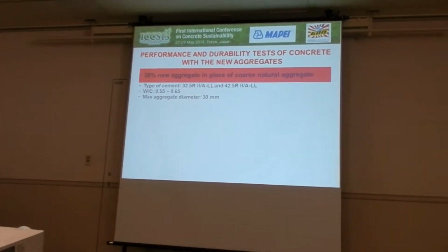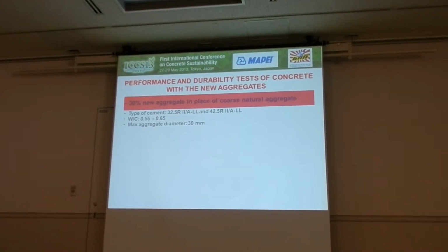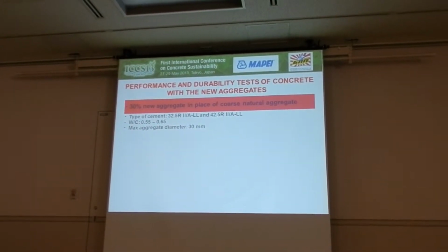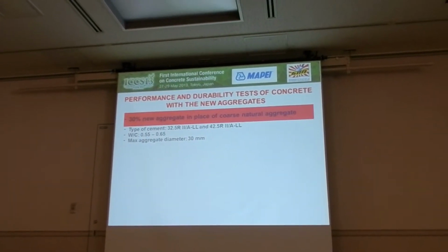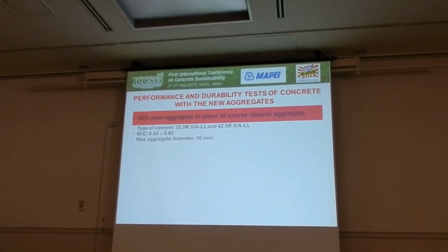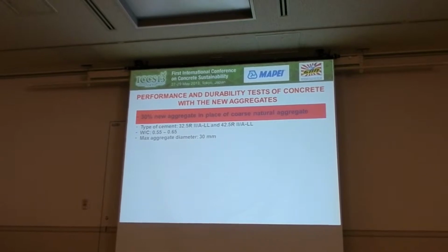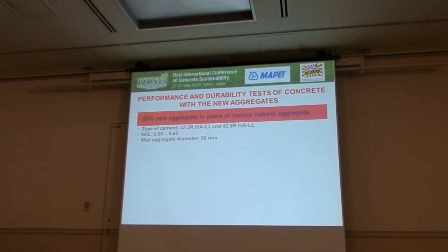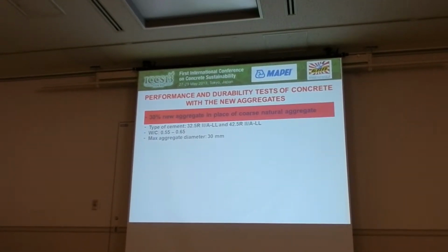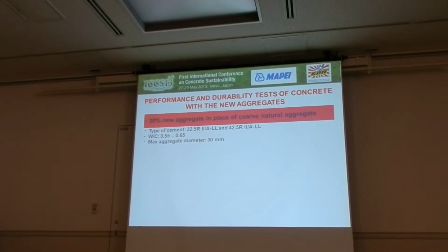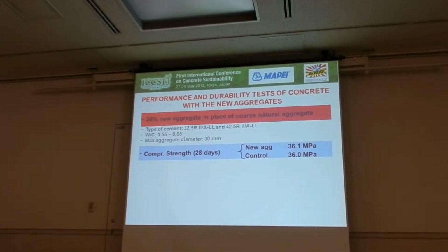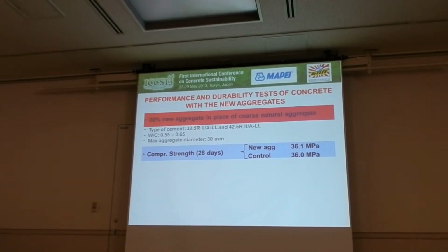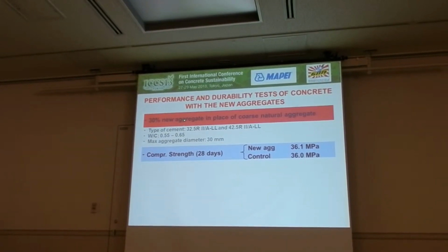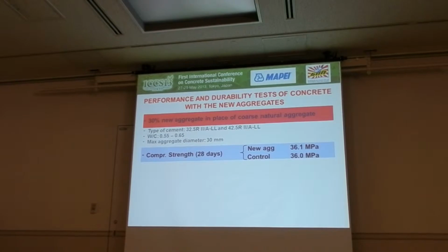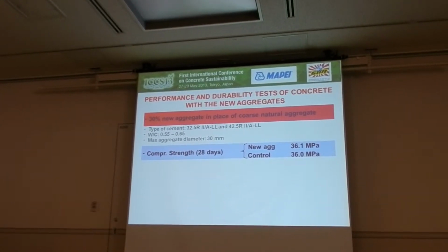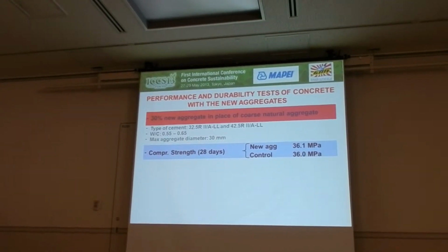What is the performance of the concrete made by using these aggregates? We made tests by substituting 30% of new aggregate in place of coarse natural aggregate. We used different Portland cements, 32.5 and 42.5, and different water to cement ratios according to the test we would do. In all the concrete, the maximum aggregate diameter was 30 millimeters. We can see that there is no effect on compressive strength comparing the concrete made with 30% substitution of new aggregate in place of natural one to the control. Control was a similar concrete but made with 100% natural aggregate.